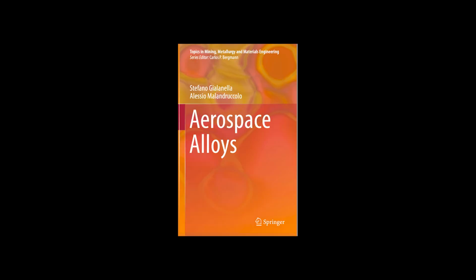Okay. Abrasive coatings can be put on the blade tips themselves. These are hard enough to cut into a compatible seal material on the casing. Examples of abradables include nickel graphite, graphite particles in nickel, or nickel bentonite, a clay mineral in a metallic matrix. The choice depends on what the rotating part is made of. You need careful matching. You wouldn't use bentonite against titanium, for instance. It's too abrasive. Fascinating. Such specialized materials for specific jobs.